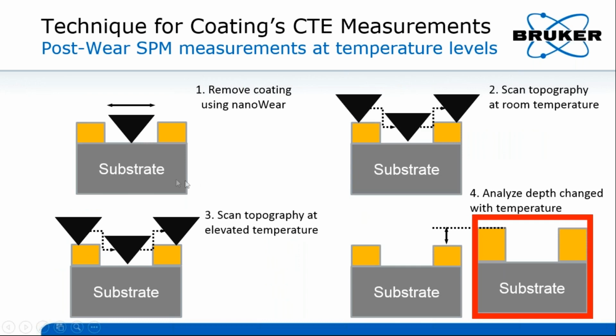Similar to Tg measurements, the main advantage of direct measurements is so significant for film CTE measurements. The 4 steps shown here illustrate how nano wear together with in situ SPM works for the CTE measurements. The first step is using the scanning wear to remove the top layer, just like the previous case about the modulus distribution in thickness direction. And the removal is not necessary to be 100%. The key point of the first step is to create a height difference within the film.